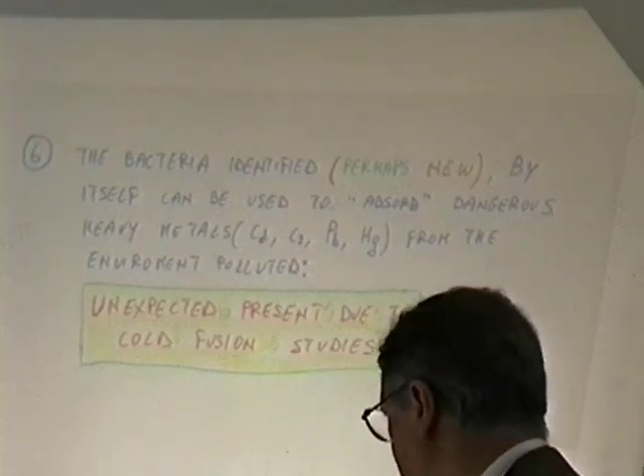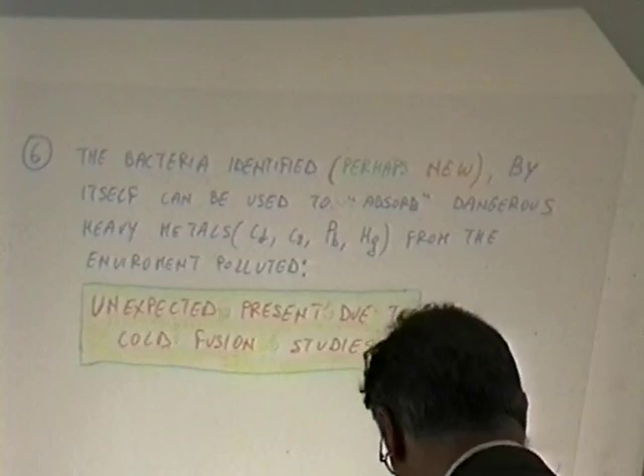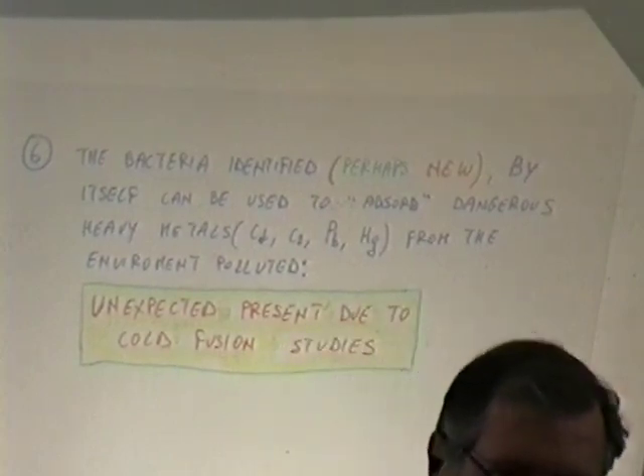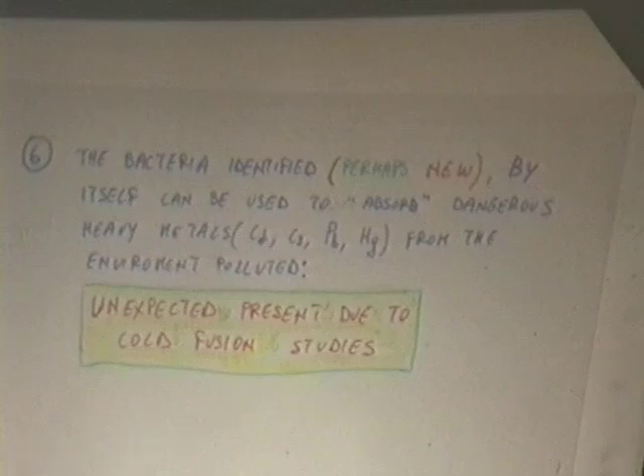You mentioned you had the 4 millimeter long active spots. How did you know that was active? We use what they call an infrared gun, so you can inspect the wire, moving the infrared gun, and we have found in some small areas of the wire an increase of the temperature with respect to the water before, or of the wire, of about 1.1 degrees in one spot, and the other 0.7 degree. It's really unexpected. So there are some odd spots.